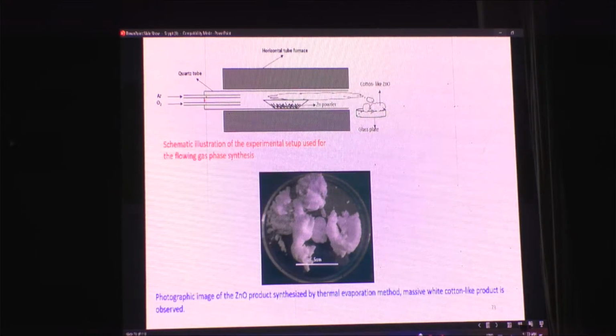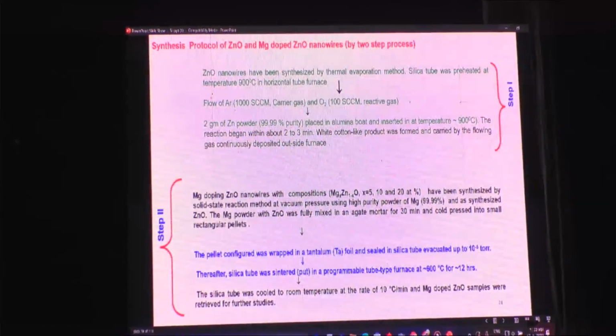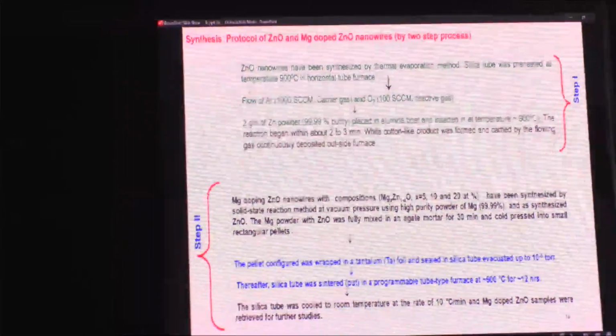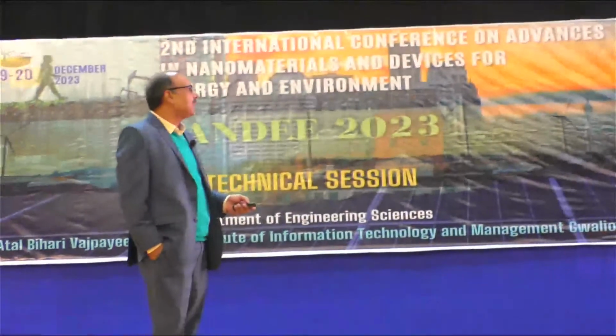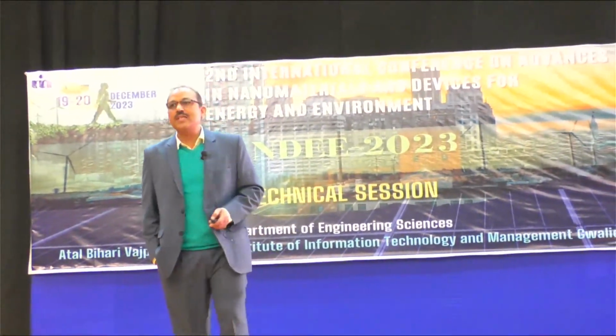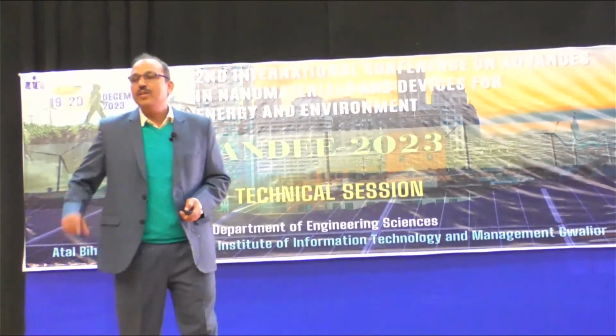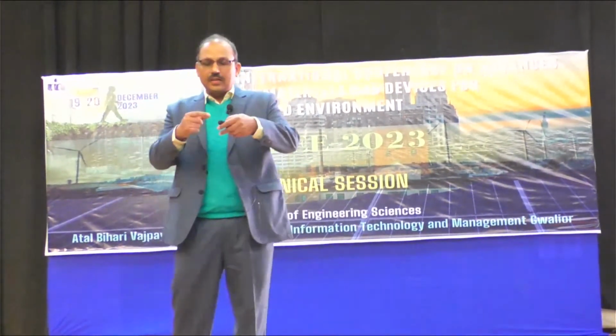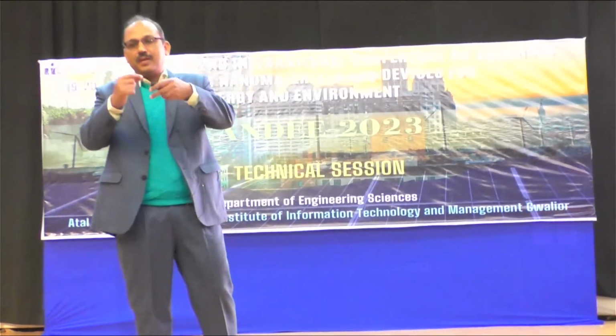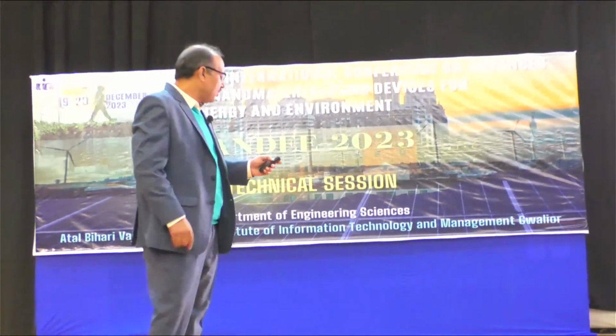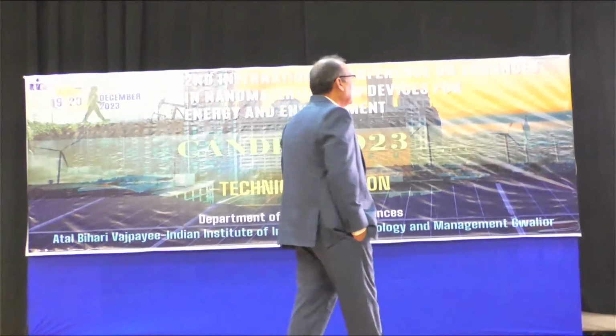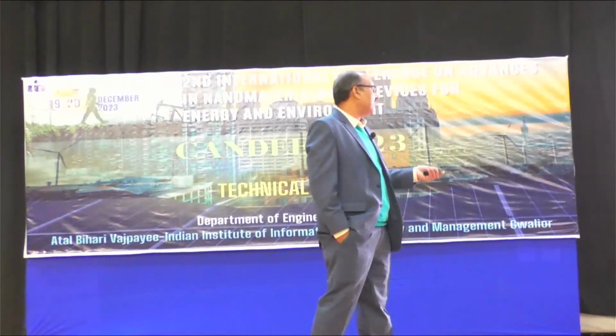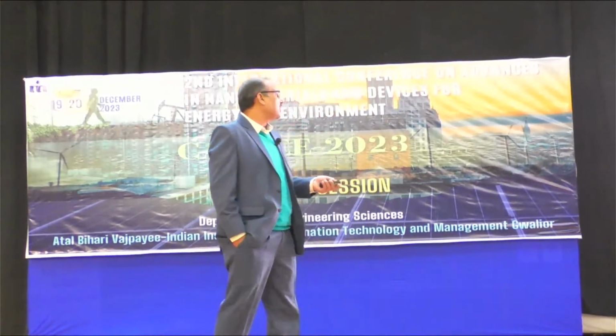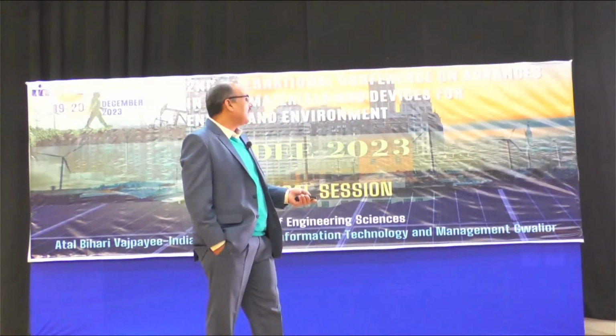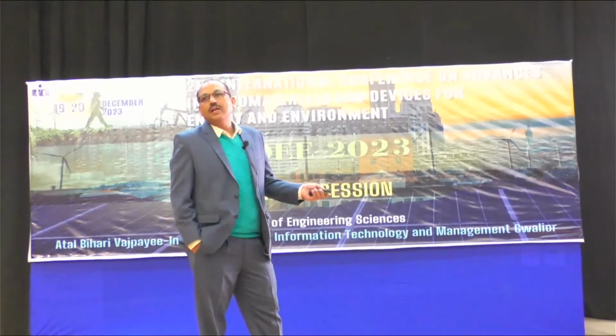So we deposited the zinc oxide, which looks cotton-like. For magnesium doping we opted for a two-step process. First we grow the zinc oxide nanowires, and after that we use the magnesium dopant. Because magnesium oxidizes easily and forms magnesium oxide, we use tantalum tape: we make a pellet and cover it with tantalum. It is used in a vacuum, and we used only about 600 degrees centigrade for annealing, which is further used for catalyzation as well as the hydrogenation process.